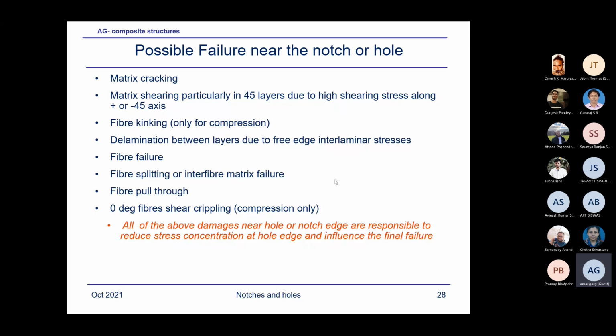Again, possible failures near the notch or hole: matrix cracking, matrix shearing, particularly in 45 layers due to high shearing stress along plus or minus 45, fiber kinking only for compression, delamination between layers. In fact, all these you can see in my previous pictures, these various failure modes mostly. They're all mixed, but this is what we have shown. Okay.